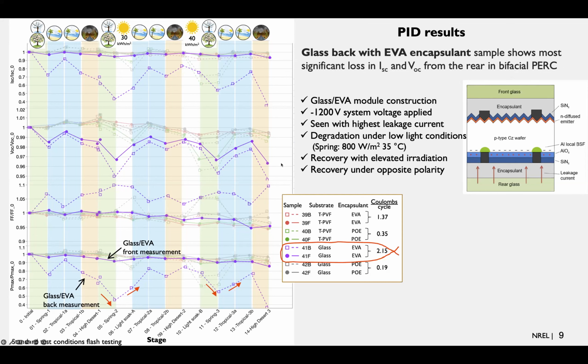So more or less consistent with, well, I should say consistent with, PID polarization. This kind of degradation was associated with the glass EVA module construction. It did occur with negative 1,200 volt system voltage bias applied to the cells. These particular modules shown here with the glass EVA in purple did exhibit the highest leakage current. And the degradation was under low light conditions, that's to say in spring. Especially here in the spring is where it degraded the most. And again, here in green, it degraded the most.